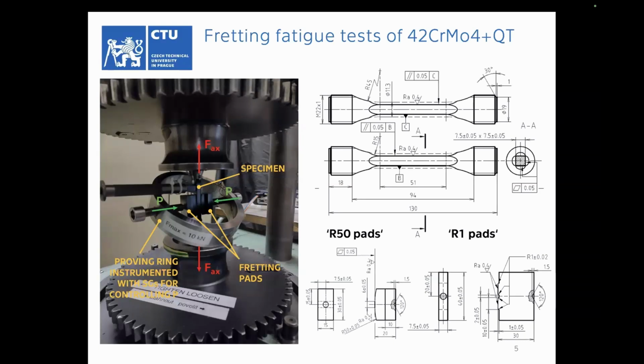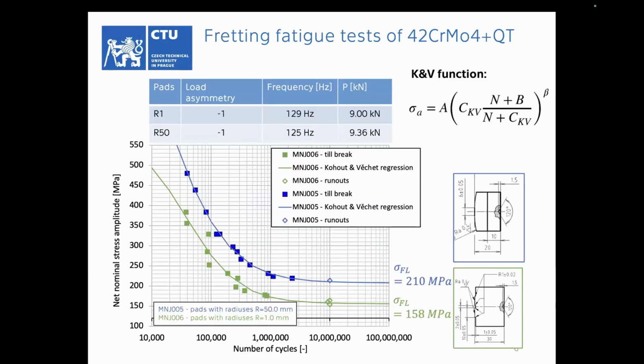It employs a simple proving ring to control the contact loading. We have used specimens with square cross section and two types of contact pads. One has a single fret surface with large radii, and the other has two contact surfaces, the so-called bridge type. The idea behind it was to get as large a range of contact slips, and therefore as large a range of generated temperatures in the contact as possible, so that we test if the method works in different conditions.